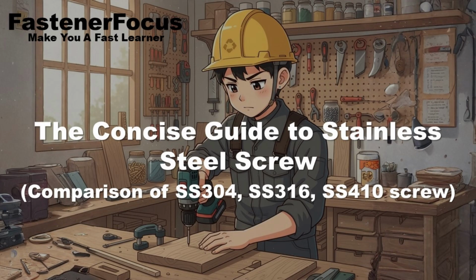Next up, nickel, Ni. The structure stabilizer, the ductility enhancer, and the element most responsible for price volatility. Nickel is critical for stabilizing that austenitic FCC structure. Grade 304 contains 8 to 10.5% Ni. Grade 316 is even richer, ranging from 10 to 14% Ni. Contrast this sharply with grade 410, which contains less than 0.75% nickel. This low nickel is what compromises 410's corrosion resistance, but paradoxically allows it to be heat-treated for its superior mechanical